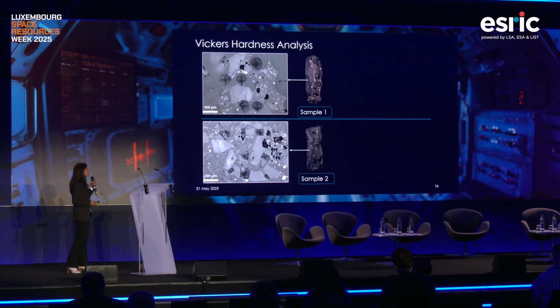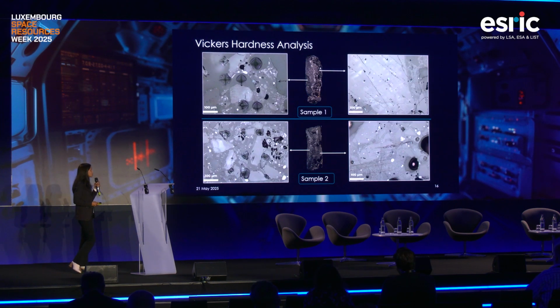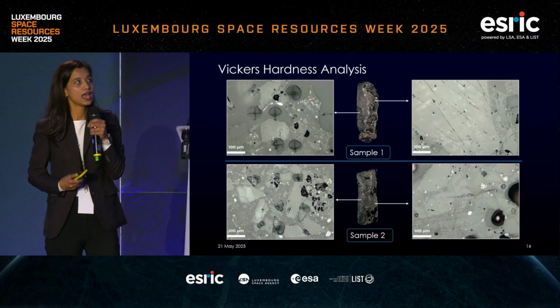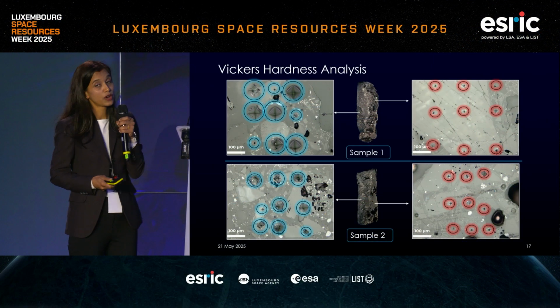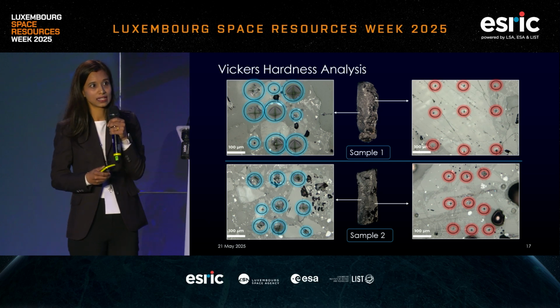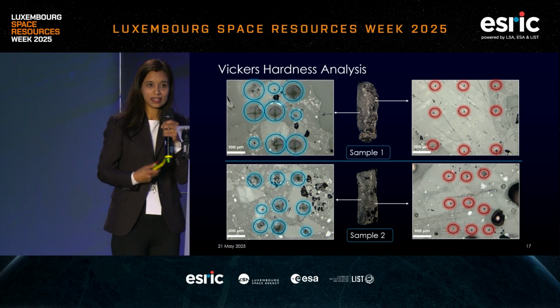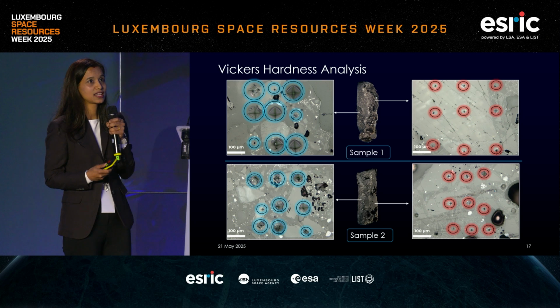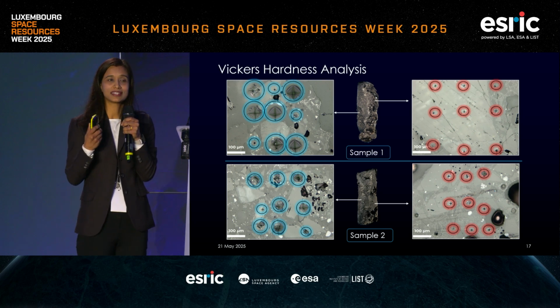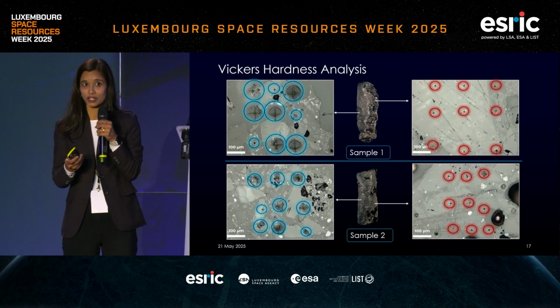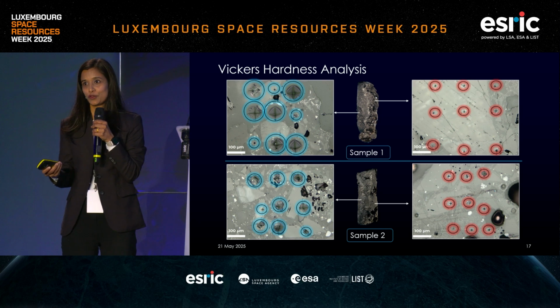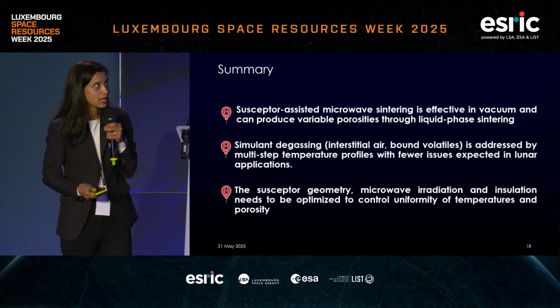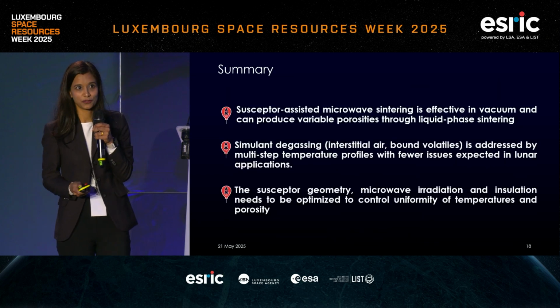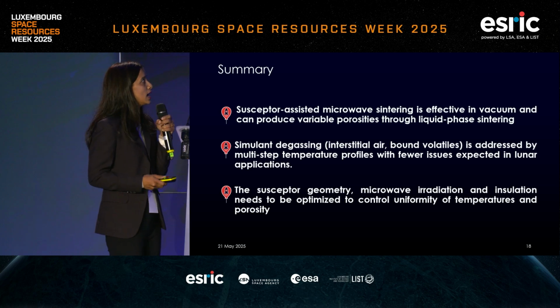So we picked up, again, the zones from low temperature and high temperature. We could easily see that the low temperature zone showed quite a few large indentations, and the high temperature zone had very small and clear indentations, indicating that that zone has higher hardness than this zone. So at this stage, it is difficult to assess the effect of different temperatures on the quality of the final product, but it definitely helps in identifying some key parameters.